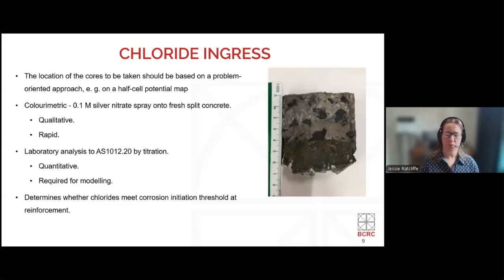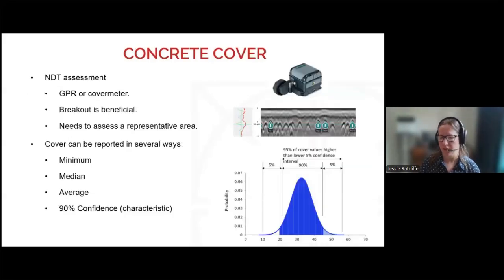This test is fairly quick, but it doesn't tell us the specific amounts at each depth in the core. So to find that, we need to do lab analysis where we grind up each level and find the amount of chlorides via titration. This gives us quantitative information on chloride levels that we can use for our modeling.